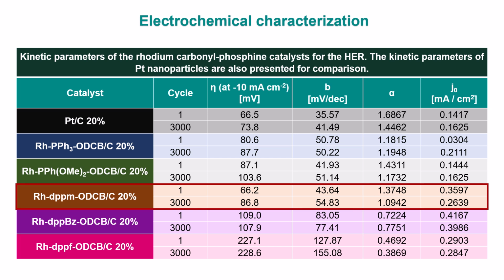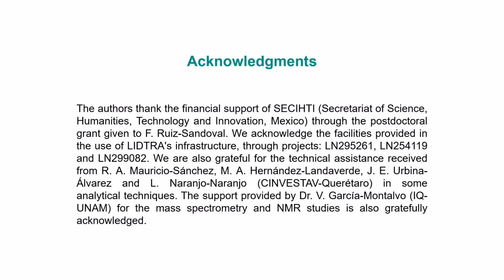In contrast, the DPPBZ, and especially the DPPF derivatives, exhibited higher overpotentials, highlighting the important role of ligand design in determining the electrocatalytic behavior. These results demonstrate that tailoring the coordination environment of rhodium clusters is an effective strategy to enhance HER performance. Their high activity and good electrochemical stability make these materials promising candidates as cathode electrocatalysts for proton exchange membrane water electrolyzers, while contributing to reduce the dependence on platinum-based catalysts.